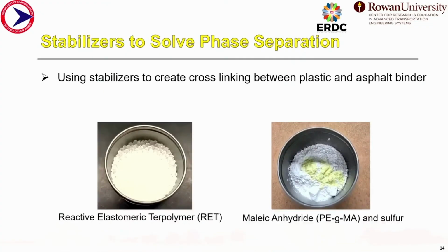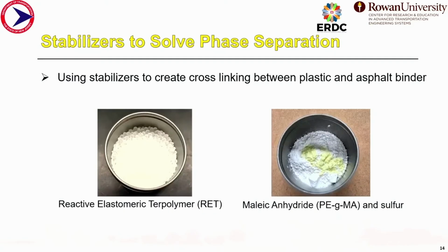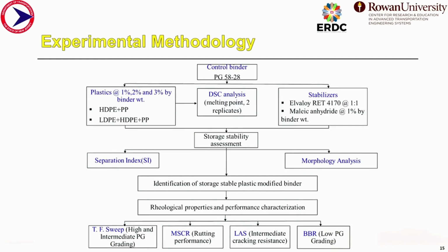And the stabilizers that have been selected are reactive elastomeric terpolymer, which is known as RET, and another one is polyethylene-grafted maleic anhydride, which is PGMA, and sulfur as a cross-linking agent. And this is the experimental methodology that has been followed for the experiments.